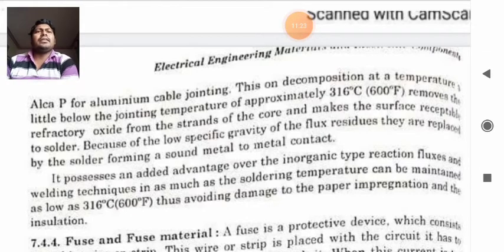Because of the low specific gravity of the flux residues, they are replaced by the solder, forming a sound metal to metal contact. Now, it possesses an added advantage over the inorganic type of flux and welding techniques, inasmuch as the soldering temperature can be maintained as low as 316 degrees centigrade, thus avoiding damage to the paper impregnation and the insulation.